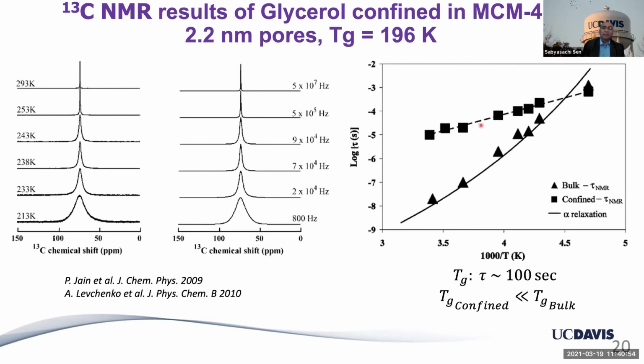So now, the problem is that the glass transition of this guy is 196 Kelvin, which is confined in these 2.2 nanometer pores in MCM41. On the other hand, the bulk TG is 185 Kelvin. So this TG of the confined glycerol we know is higher. But then TG is defined as the temperature where the tau is about 100 seconds, right? So it'll be 2 on this scale. And you can see if I extrapolate these two curves to a value of +2, then the temperature corresponding to the confined one would be extremely low compared to the bulk. So this is the reverse of what we are actually observing.